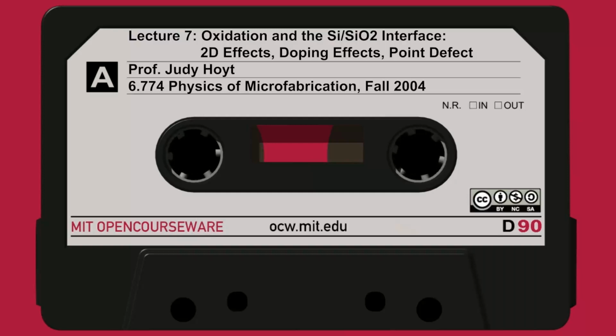That's some hint. What I started to talk about, which I think to me is a little more convincing, is that maybe this is really to do with vacancies. If you look at the oxide thickness as a function of the electrically active phosphorus, this solid line is for uncompensated. What is uncompensated? I just add phosphorus at a certain level. Here I add it at 10 to the 19th, 5 times 10 to the 19th, 10 to the 20, and 5 times 10 to the 20. And I don't add any other dopants, no boron. As the phosphorus goes up, the vacancy concentration goes up, and so does the thickness.